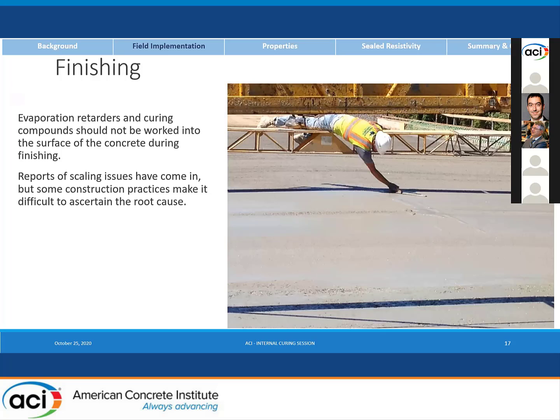There's conversation about whether or not these bridge decks had, a couple of them, some scaling issues, and I would say that it's probably going to be hard to determine what the real underlying source of those are. So we shouldn't be working things into the surface during finishing, primarily because those products are 80% water, at least in a lot of these cases.